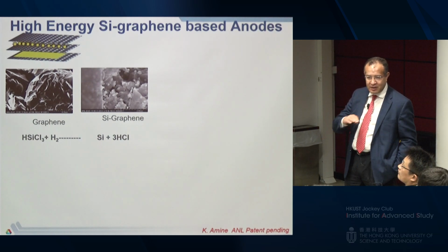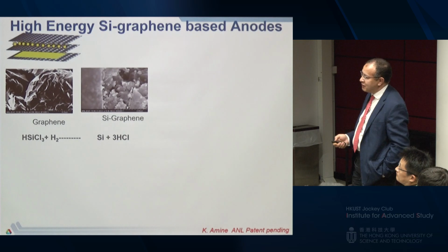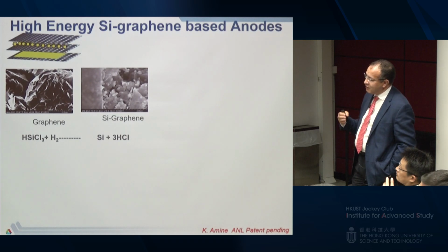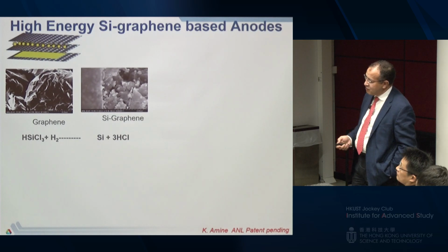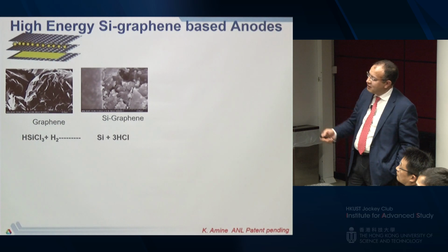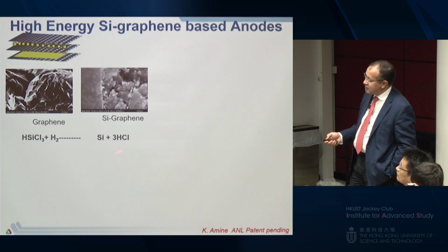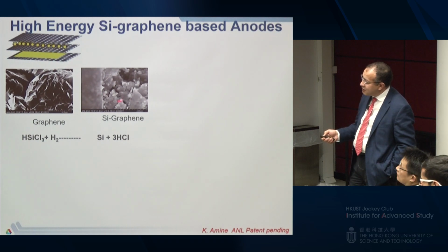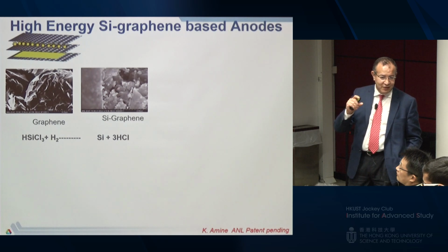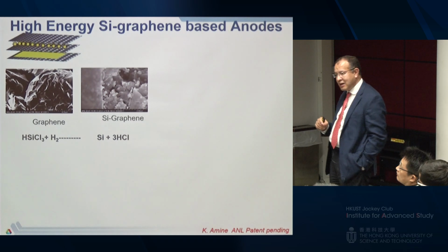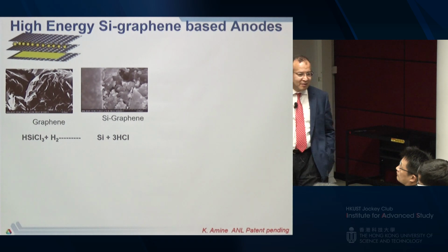It doesn't have to be fancy monolayer, whatever, just like this. And graphene has sheets, so you put this in a reactor and you reduce this gas. This is a gas, gas goes everywhere, obviously. You reduce it and you form silicon. And since you do that in the gas phase, the silicon particles are already at the nano phase. So nano does not crack immediately. It will take longer to crack, obviously.